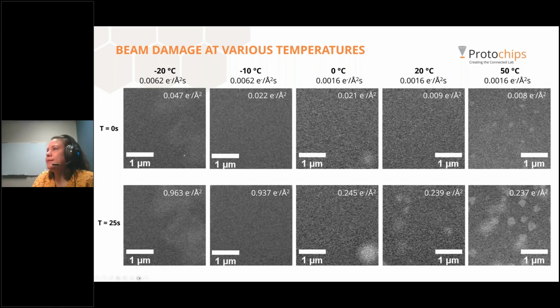And you can see that there doesn't appear to be a whole lot of change at -20, maybe a little bit. Could not find any particles to focus on there. It did start growing at -10. At 0, I could find a little one that seemed to grow. And then at 20, we definitely start to see some nucleation of beam-induced damage. And at 50, it was obvious. The next slide, I actually show videos of this occurring.